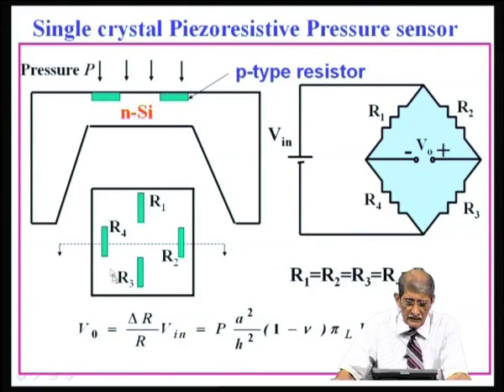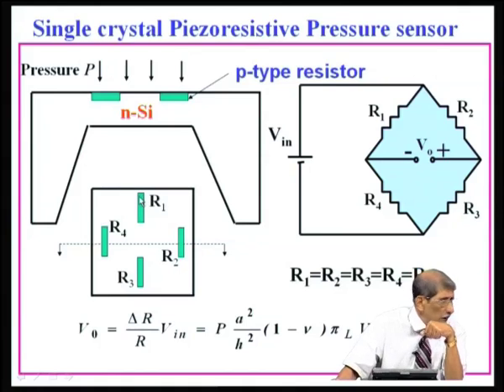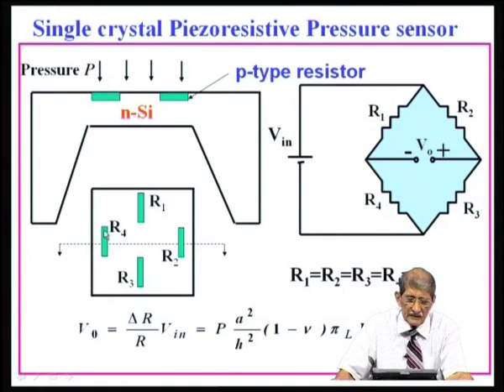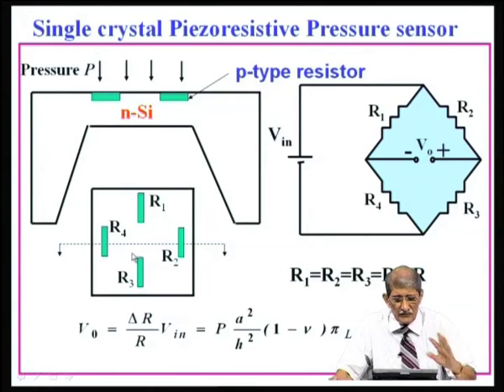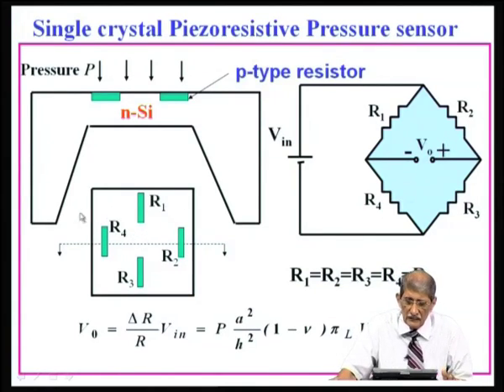So, the four resistors are located like this, R 1, R 2, R 3, R 4, because at the edges, in the middle at the edges, the stress is maximum. Longitudinal here, longitudinal here, transverse here, transverse here. That is the key thing. Two of them should increase, the other two should decrease. That is why you choose these locations.